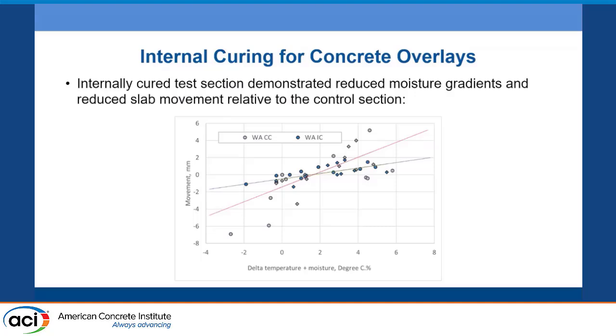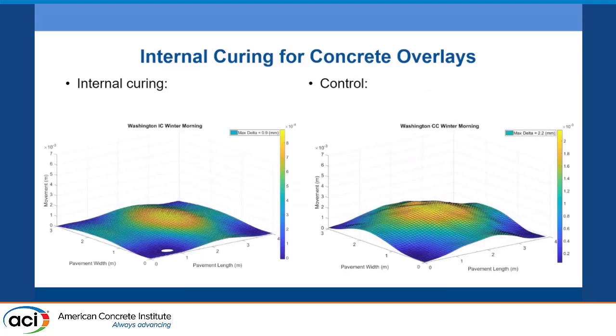So obviously this scatter plot here is just showing the gradient versus the movement that they measured through LiDAR, but it's probably easier to look at this from a visual. And these are kind of the results. The picture on the left there is the LiDAR scan at one particular visit. It looks like it was in the winter in the morning where they looked at this section. And you could see an overall flatter profile there for the internal cure section relative to the conventional section.